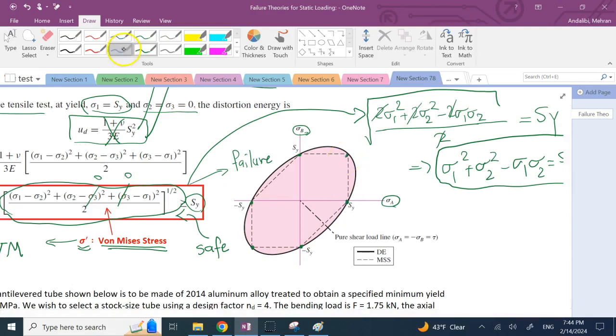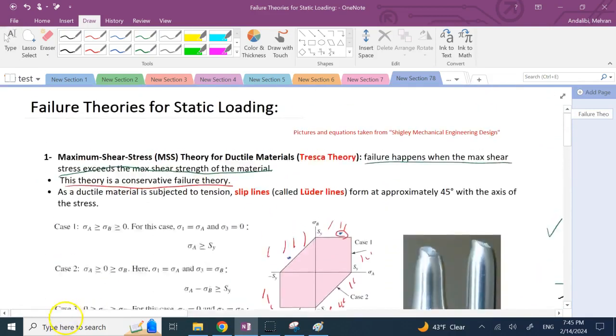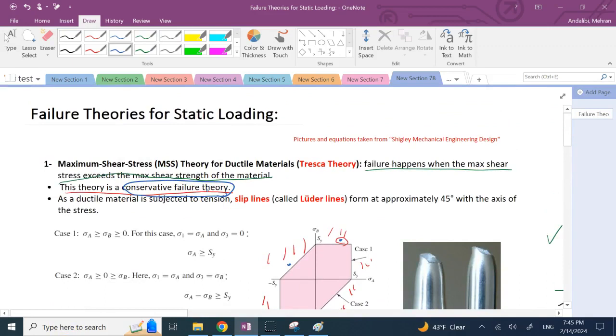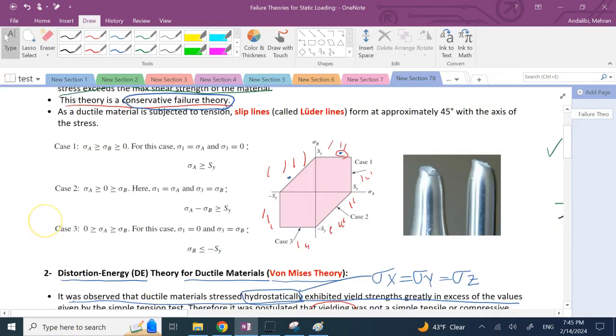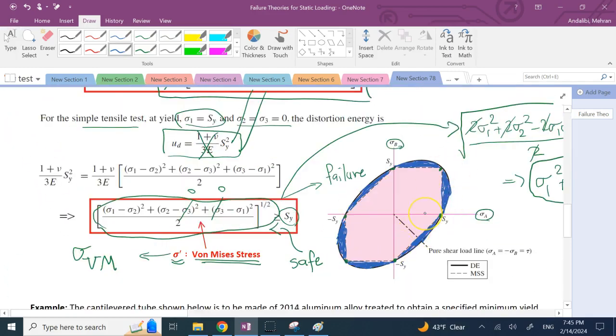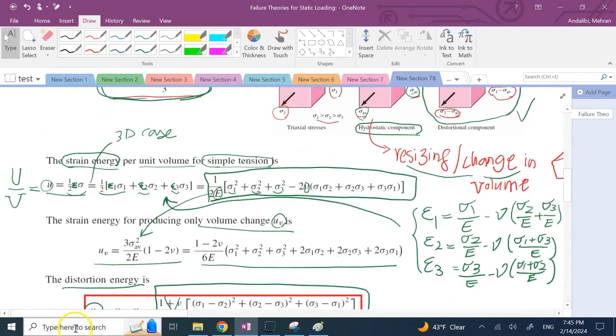So this method says not only inside Tresca is safe, actually all of these regions that I'm going to paint in blue for you are also safe. Because these are the regions where the strain energy does not surpass the one that is for failure, because a portion of it is used just for changing the volume of the material, and not all of it is used for distortion and shear. You see? So the Tresca gives you a smaller region compared to the von Mises. That's why we call the Tresca method a conservative one. Because it does not allow too much motion outside this hexagon, but von Mises gives us a little bit more wiggle room. Okay, so this was the von Mises stress, or the distortion energy.